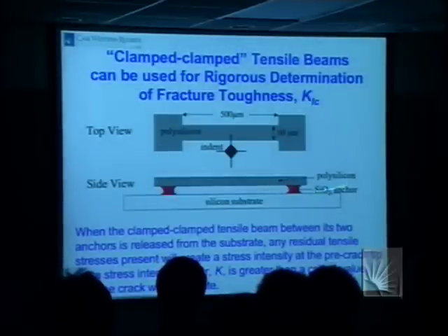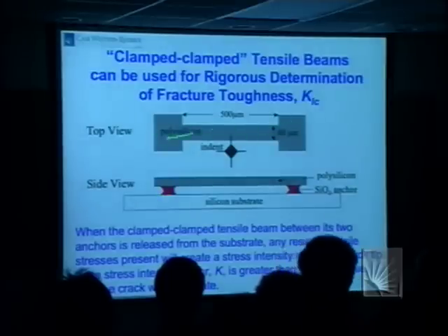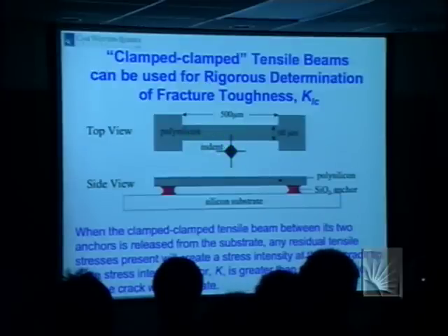So here's the schematic of the device. It's what I told you. It's this clamp beam. This is the oxide that's still anchoring the beam. Here's our test specimen. Here's the indent. There's a crack, and it ran through and into the material.